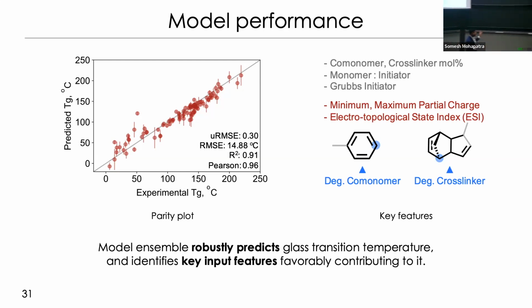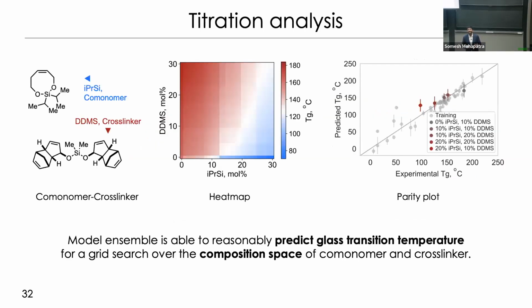On the basis of that, we really wanted to make sure that the model had understood the entire composition landscape. So we did a grid search over 0 to 30% of the co-monomer isopropyl silyl ether and another cross-linker, DDMS, from 0 to 30%, and looked at what the model sees in terms of trends across this entire set. If you increase the cross-linker to 30%, it should have the highest TG, which was slightly greater than 180.